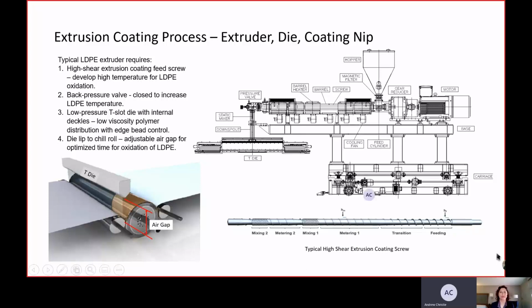So this next slide, I go into a little detail of the extrusion part of this extrusion coating line. And the extruder for extrusion coating is assembled on a cart so that it can be brought into the machine to coat. We have the extruder with the feed screw in the barrel of the extruder, pumps the polymer through, typically through some kind of pressure valve, and down into a T-slot die. This T-slot die is positioned over the moving web, and the polymer is spread out through the die where it comes out as a thin film, which is then drawn from the lips of the die at a very low speed into the coating nip at a high speed.